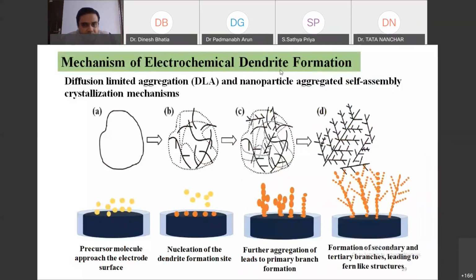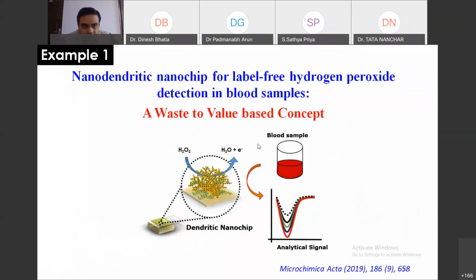So this is the mechanism of the electrochemical dendrite formation, where you have a precursor molecule, and after this precursor molecule there is a nucleation of the dendrite formation, and with time it keeps on growing and eventually forms the 3D structure, something like this. So this is the cartoon of that, and in the whole process of the formation, the diffusion limited aggregation is actually happening. So this is the pictorial representation, and when we go into more detail, I'll let you know how it looks onto the surface.